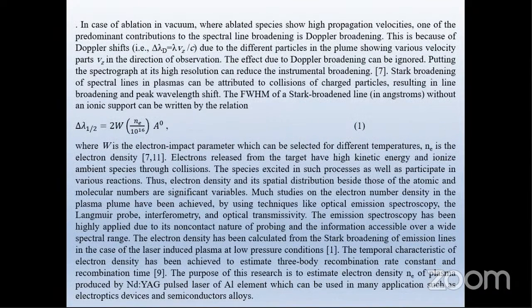In case of ablation in vacuum, where ablated species show high propagation velocities, one of the predominant contributions to the spectral line broadening is Doppler broadening. This is because of the Doppler shifts, i.e. delta lambda D equal to lambda V sub Z over C, due to the different particles in the plume showing various velocity parts, V sub Z in the direction of observation. The effect due to Doppler broadening can be ignored. Putting the spectrograph at its high resolution can reduce the instrumental broadening.